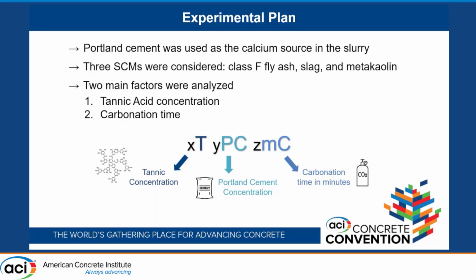so no tannic acid versus adding the tannic acid, as well as the carbonation time. So here's just a little diagram for you to follow along. This is how all of the samples are labeled. The T indicates the tannic acid concentration, and PC indicates the Portland cement going into that initial slurry. And then the MC indicates the carbonation time in minutes.